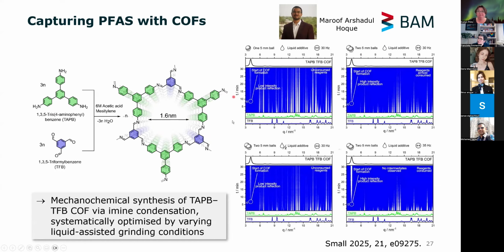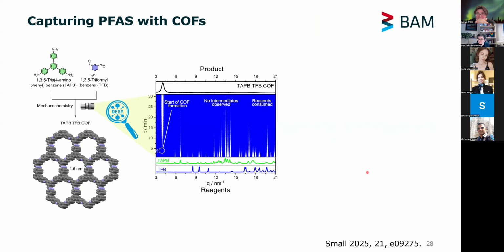And here again, I'll show you in situ data, which show basically that it's possible to optimize the synthesis conditions. You know, COFs are a bit boring when it comes to X-ray diffraction, or at least underwhelming. But you can see here that we chose different milling procedures, and then in the end also reached a higher crystalline material that could be then subjected to adsorption tests.